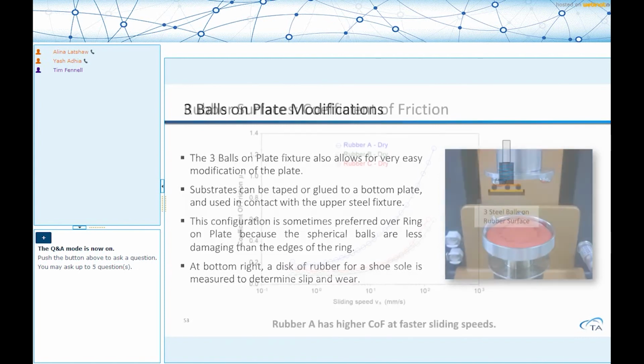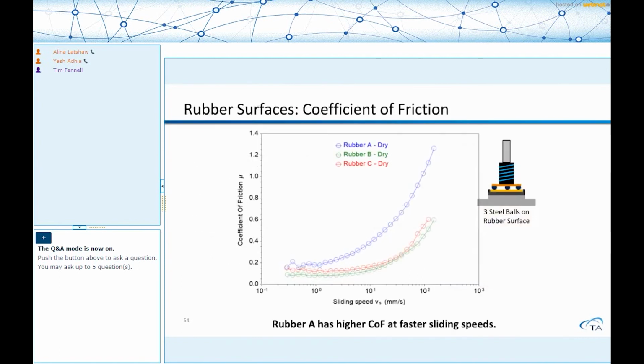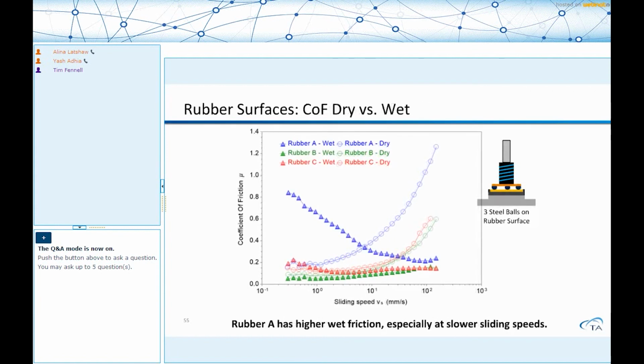Okay. So now, if you just take dry surfaces, so you have steel balls on the top, rubber at the bottom, at slower speeds the coefficient of friction is more or less comparable to B and C. Now, if you add a layer of water and then perform the measurements, you're simulating wet grip of this material. And you can see how the wet grip of the material is quite different. Wet grip starts showing differences at the lower sliding speed, and then as you start increasing the sliding speed, it becomes more and more comparable. So that's again the benefit of this setup. Much more difficult to do on 3 balls on a plate.